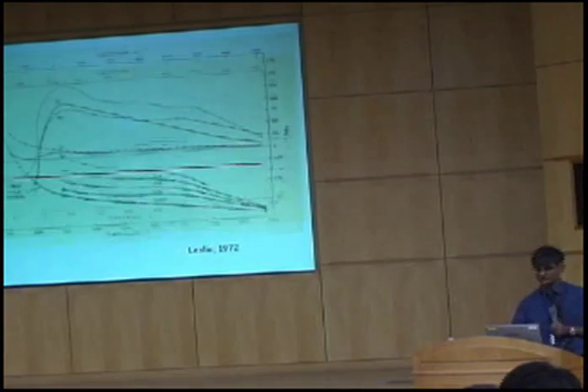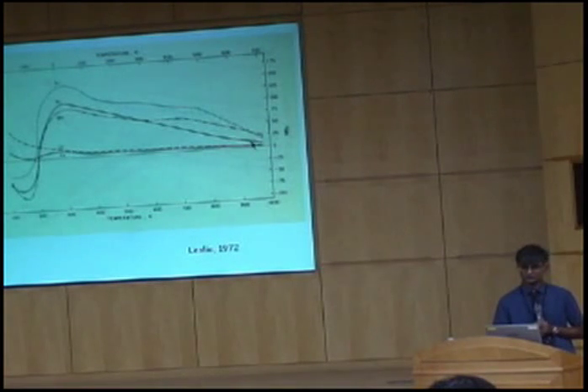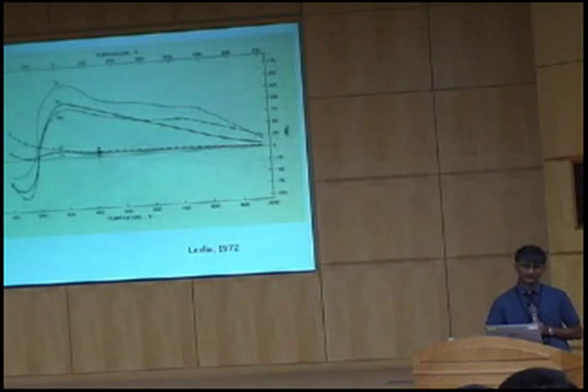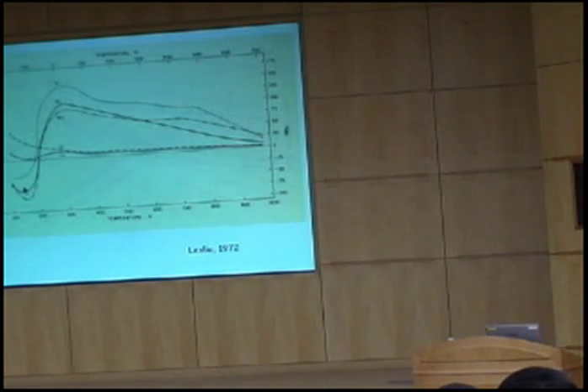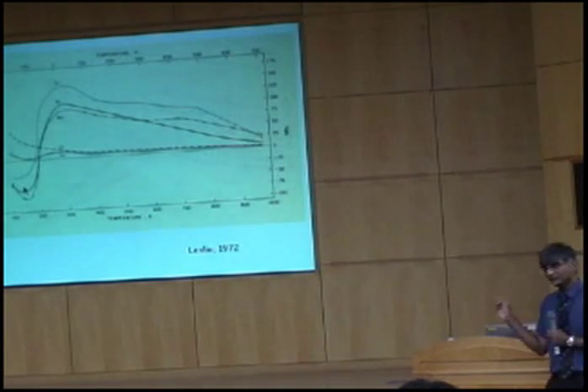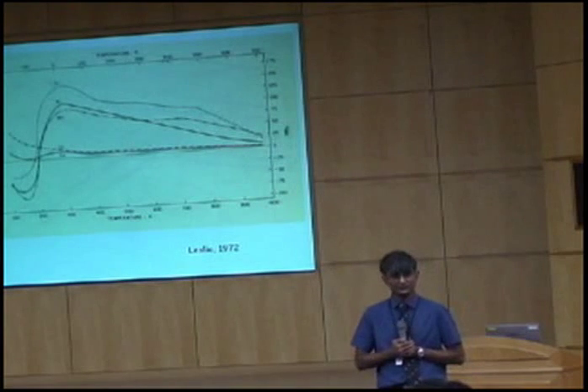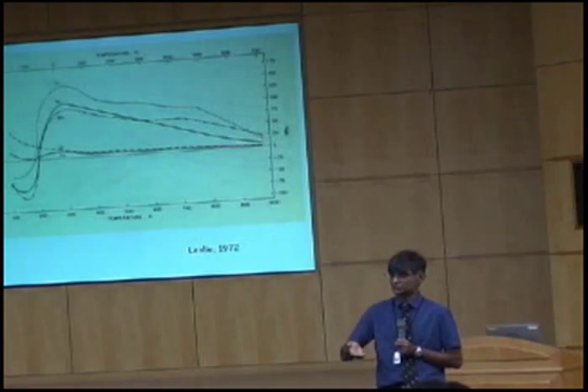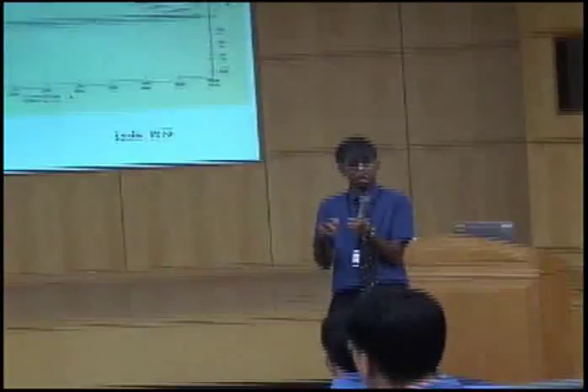So for example, if you look at the solid solution strengthening due to nickel, at high temperatures it's not making much of a contribution. It has the largest contribution near to room temperature. This is in Kelvin here. And at very low temperatures it even causes solid solution softening. Because I explained to you that at low temperatures the flow stress is very sensitive to temperature, so there is a large barrier to dislocation motion. And if you put a solute atom inside the crystal which disturbs the crystal, then it helps the dislocation to surmount a barrier. So at low temperatures many of these solutes actually cause softening rather than hardening. But you're talking about temperatures well below room temperature.